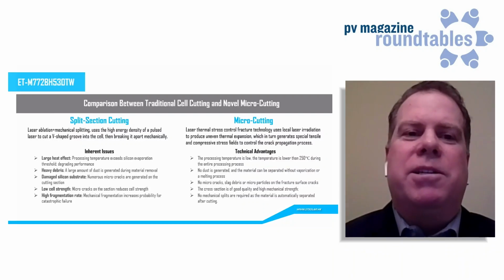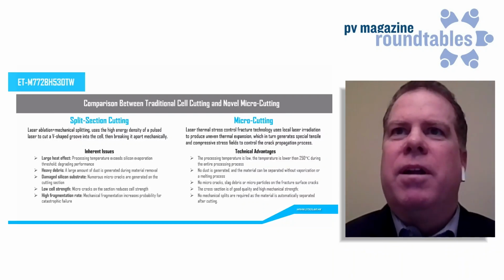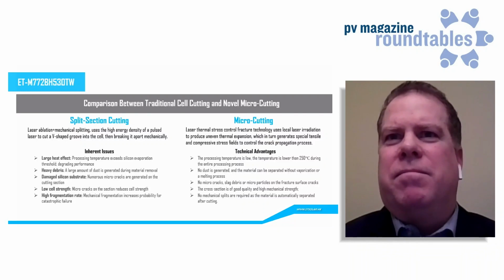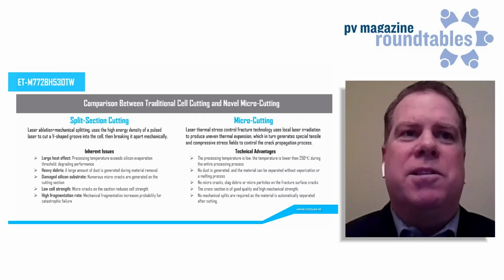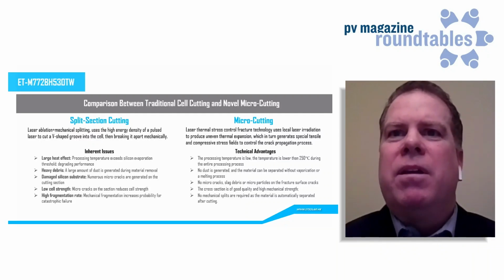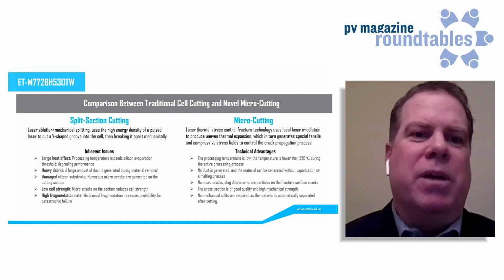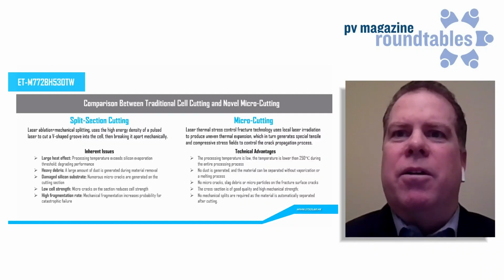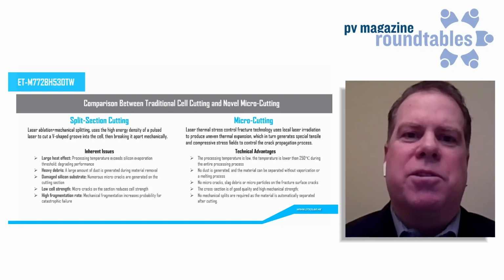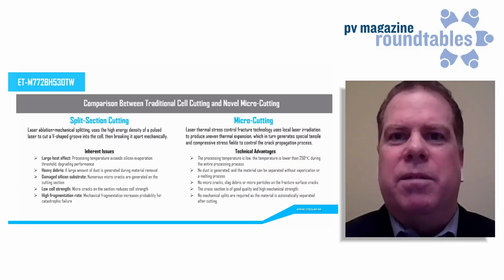So some of the advantages to this novel approach for cell cutting is that it utilizes a lower power laser. The temperature is low and does not cause any kind of heat damage to the silicon. There is no dust generated. The material can be separated without the vaporization or any kind of melting process to the material. There are no microcracks or microparticles that result from the fracture surface cracks. And the cross-section is of good quality, high mechanical strength, which is extremely important when this is all strung together and put into the module.